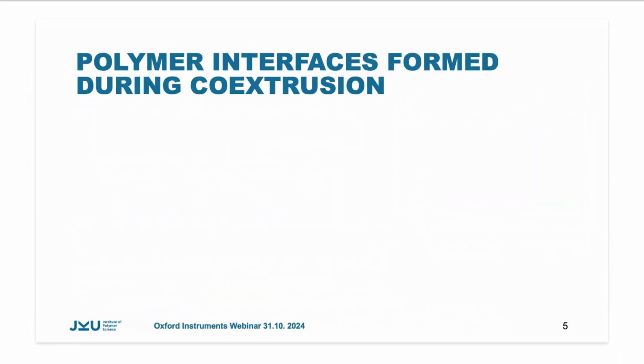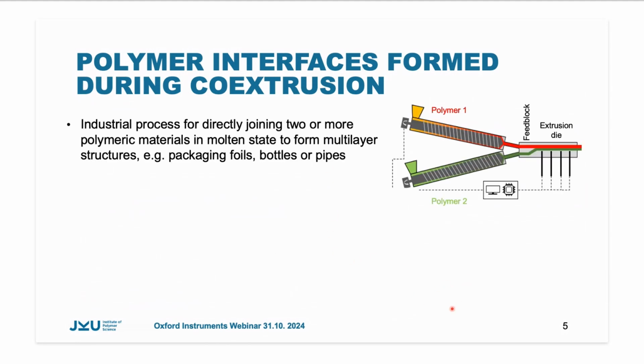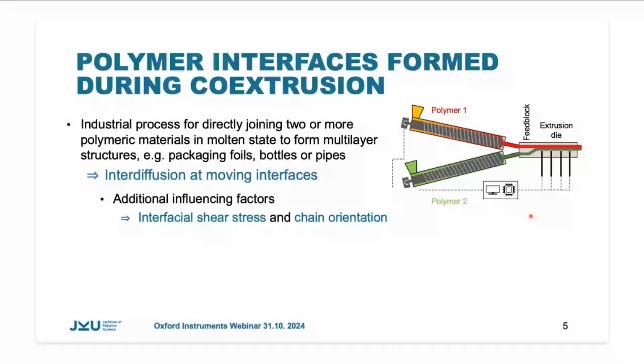Polymer interfaces can be formed under different conditions. One example is the co-extrusion process. This is an industrial process where you directly join two molten polymers to form multi-layer structures like packaging foils, bottles, or pipes, as shown here in the sketch. Here, interdiffusion happens at moving interfaces. Thus, additional factors have to be taken into account, such as interfacial shear stress and chain orientation.